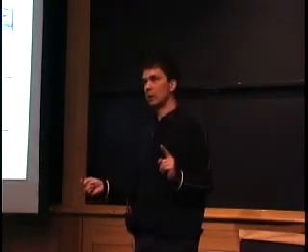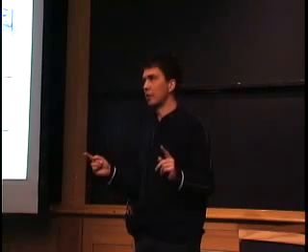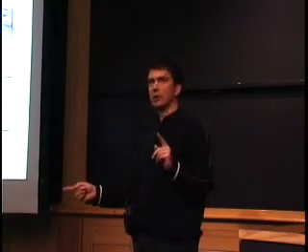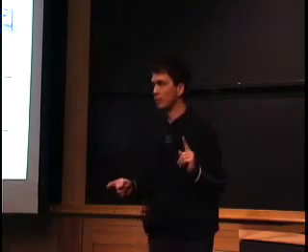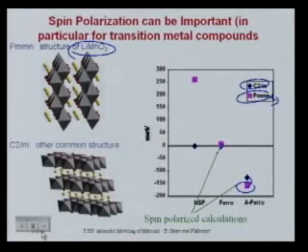Because it turns out that the biggest effect on the energy is the fact that you have that local moment. It's not necessarily how they're arranged. You can actually see that here. How they're arranged makes you go from this difference to this difference. But turning on the local moment makes you go from this difference to that difference. So never fall in that trap. It's really only non-magnetic materials or diamagnetic materials for which you don't really need spin polarization.